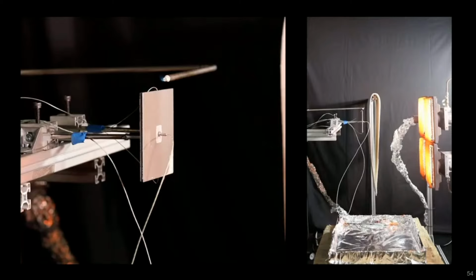Well, I'll explain to you first what we will see, and then I'll show it to you and explain it as we go. So once I let this run, we will see the radiant panel array, which is to the right in these images, move toward the sample. Our timer will start at the moment that the radiant panel array comes to rest in front of the sample. After about 30 seconds, we'll see pyrolysis gases visible above the specimen. Between 30 seconds and 1 minute and 18 seconds, the rate of production of pyrolysis gases will increase. At 1 minute and 18 seconds, ignition will occur at the top of the sample.